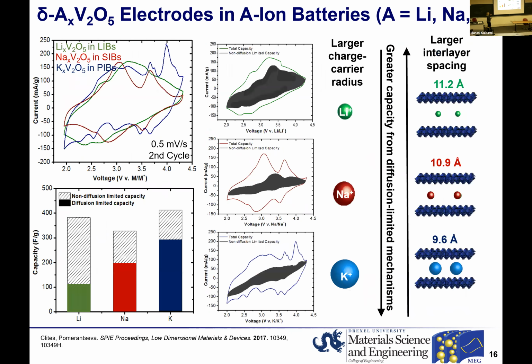And by analyzing cyclic voltammograms at different sweep rates, we calculated that in the case of potassium, we see the highest contribution of diffusion limited charge storage, while in the case of lithium, the highest component comes from the non-diffusion limited contribution. And this can be explained when one looks at the interlayer distance and the size of chemically pre-intercalated ions. In the case of potassium, it's the smallest interlayer distance and the largest ions, which implies that diffusion will be more critical in these materials. And for lithium, it's vice versa, small ion and the largest interlayer spacing. So diffusion is not such an issue in this case.